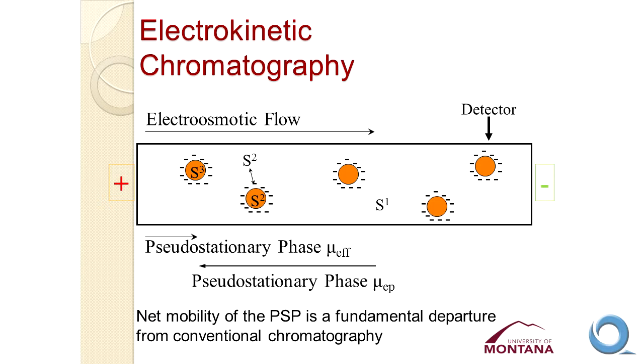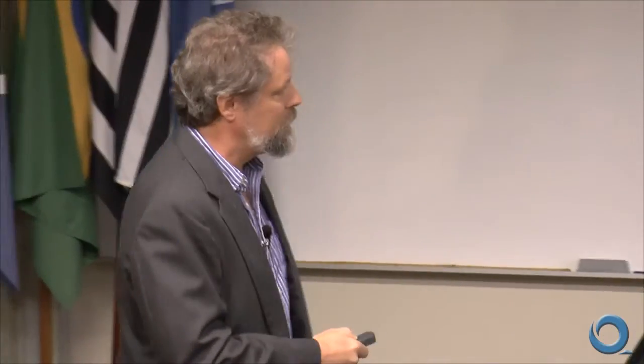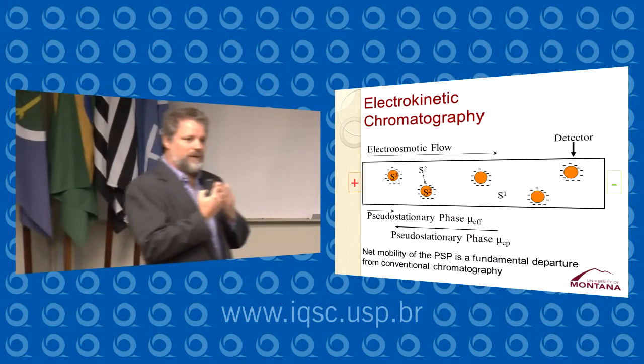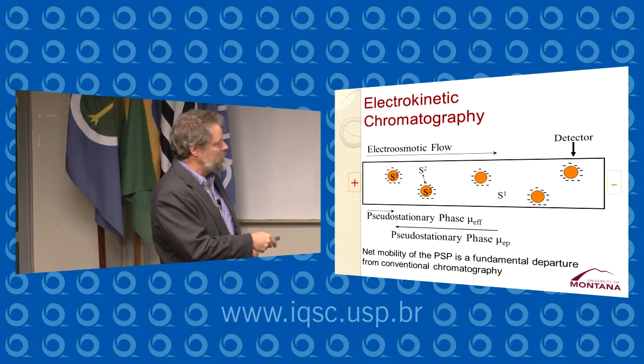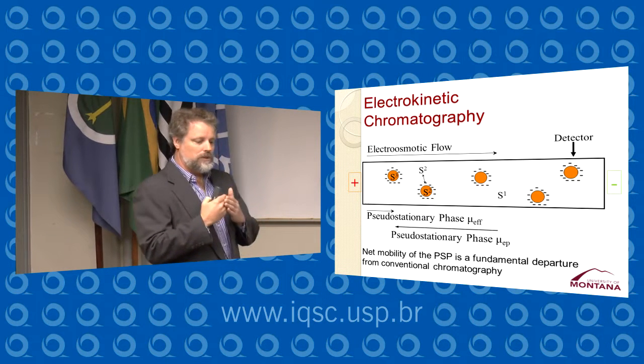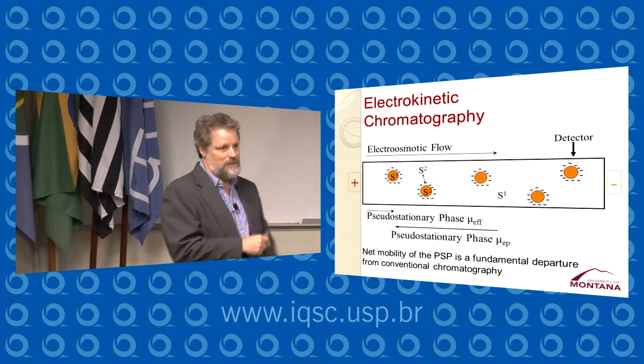So they're negatively charged, they have a hydrophobic interior, and they are soluble and dispersed throughout the buffer medium in the capillary. Now, when we apply the potential, we still get electroosmotic flow through the capillary the same way we did before. This pseudo-stationary phase, because it's anionic, will have electrophoretic mobility in the opposite direction. And so it has a net or effective velocity, which is less than that of the electroosmotic flow. So we establish a situation where we have two phases. We have the buffer, and then we have the pseudo-stationary phase, which are migrating along this capillary at different velocities.